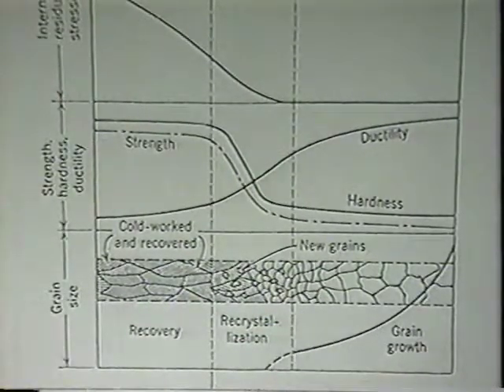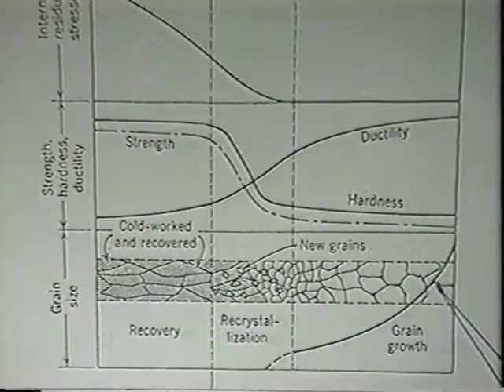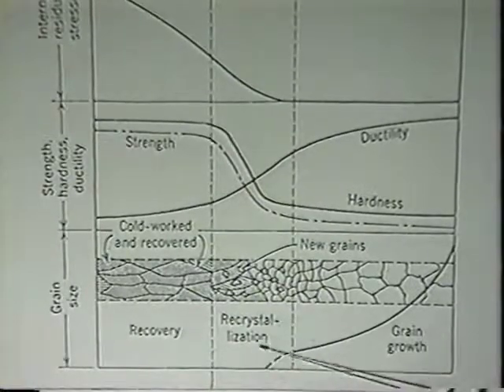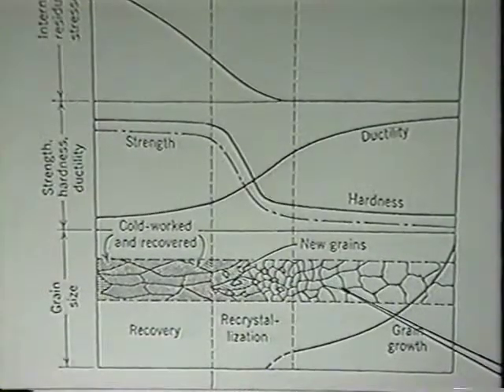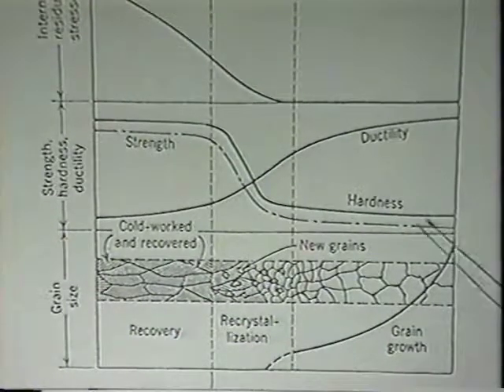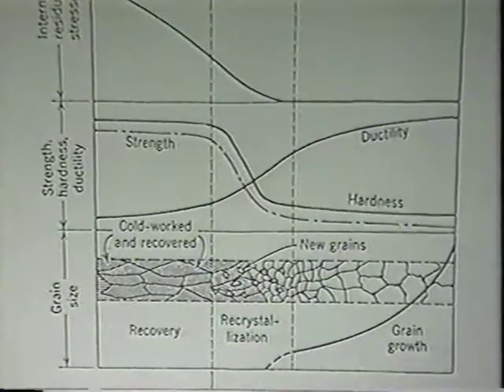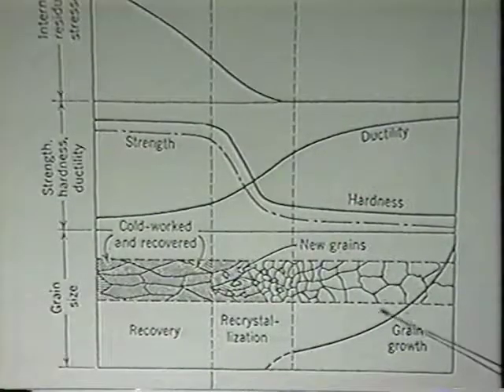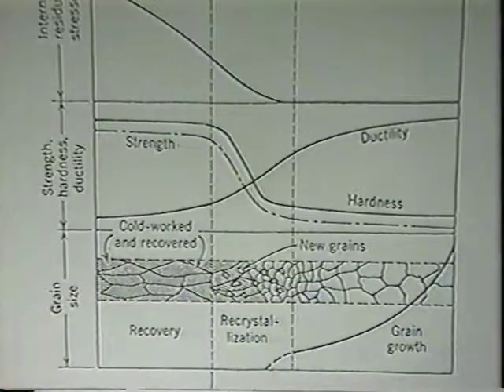If you're looking at adding to the ductility, we need a phenomenon called grain growth. And that occurs later on in the anneal cycle, through time. Recovery happens at about 1,000 degrees. Recrystallization happens at about 1,200 degrees, 1150 or 1,200. Grain growth happens at 1150 or hotter through time. Notice that while the grains are going from small equiaxed to big equiaxed, we don't have much of a change in hardness, but the ductility continues to rise. Our deep drawing quality or DQSK steels are in this range of the anneal cycle. So we recover, we recrystallize, we grow. That's the process of anneal.